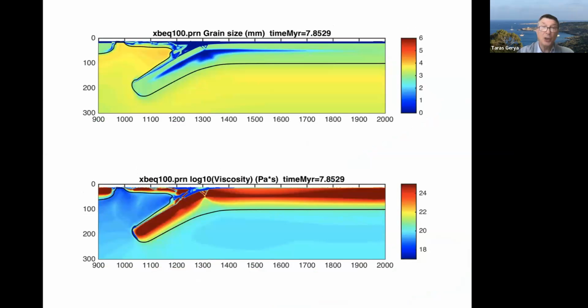So at a higher magnification, we start to see how this feedback happens. On the top, we develop strong focusing of normal faulting. Instead of being distributed, it starts to be localized, and we have large offset normal faults, which are also very well visible here. And then beneath these large offset normal fault regions, which develop very close to the trench or underneath the forearc at shallow depths, we see this viscosity reduction triangle, which is characterized by very low grain size under conditions of focusing of deformation and very large stresses, which are leading to dislocation creep and associated grain size reduction.